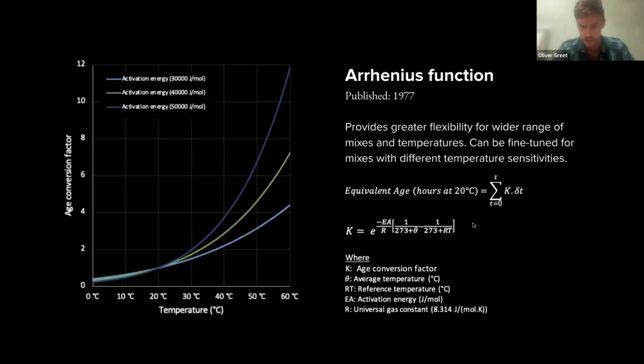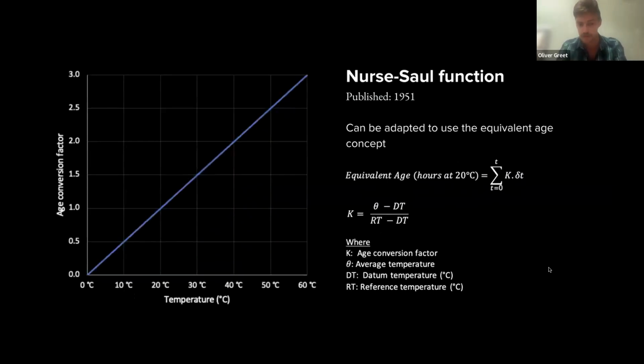Again, as the research went on, that was in 1951. A second function was published in 1977. Actually, Harshita referenced the same guy, Arrhenius. He was actually a 19th century chemist, so he didn't publish this function, but it was named after him as he published one of the original functions in pure chemistry, looking at reaction rates and how kinetics affect those reaction rates. So what you can see here is this function is considered superior to the first one. It addresses one of the main issues, which is that in practice, the suggestion that the rate of reaction is linear with respect to temperature, i.e. it doubles between 20 and 40 and would therefore double again at 80, doesn't actually hold entirely true for many concretes.